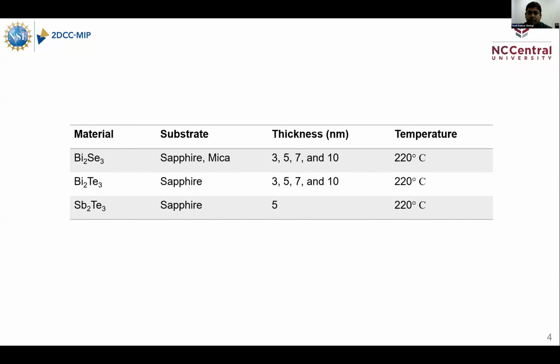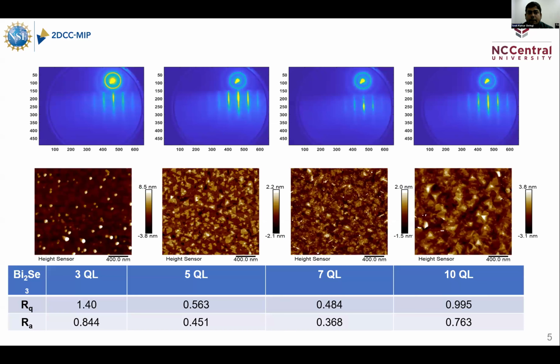The growth temperature was kept at 220 degrees. We optimized it in the range of 200, 220 and 240 degrees, and we got the best result at 220 degrees centigrade, so we chose this for the rest of our sample preparation. These are the RHEED patterns for the grown bismuth selenide samples with different thickness: 3 quintuple layer, 5 quintuple layer, 7 quintuple layer, and 10 quintuple layer.